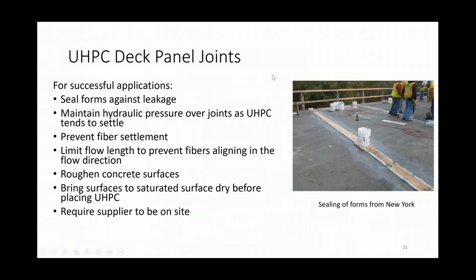All right, so here are some really key points in making UHPC work. And this is not just for these two applications, but for any application. I didn't cover it all with UHPC. So one very important thing is to really seal the forms against leakage, because UHPC is a lot more flowable than normal concrete. So that's why you see on the right hand side that there's actually a top cover as well for that form. So you do have to seal them. And it's a material that tends to settle a little bit.